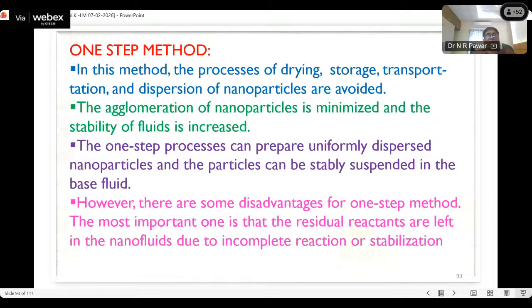Why use the one-step method for the synthesis of the nanofluid? Because in the one-step method, the processes of drying, storage, transportation, and dispersion of nanoparticles are avoided. The agglomeration of nanoparticles is minimized and the stability of the fluid is increased. The one-step process can prepare uniformly dispersed nanoparticles, and the particles can be stably suspended in the base fluid. However, there are some disadvantages of the one-step method. The most important one is that residual reactants are left in the nanofluid due to incomplete reactions or stabilization.